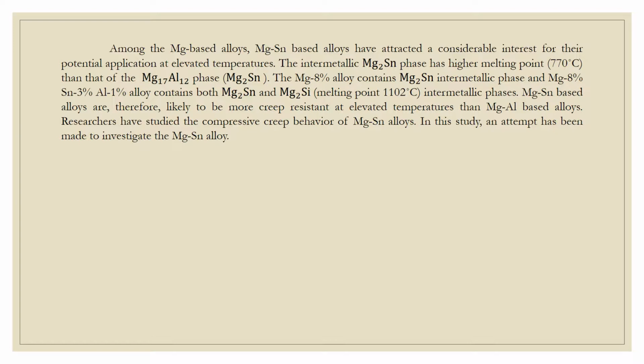The intermetallic Mg2Sn phase has a higher melting point, which is 770 degrees Celsius, than that of the Mg17Al12 phase. The Mg-8%Sn alloy contains the Mg2Sn intermetallic phase, and the Mg-8%Sn-3%Al-1%Si alloy contains both Mg2Sn and Mg2Si, whose melting point is 1102 degrees Celsius, intermetallic phases. Magnesium tin-based alloys are therefore likely to be more creep resistant at elevated temperatures than magnesium aluminum-based alloys.